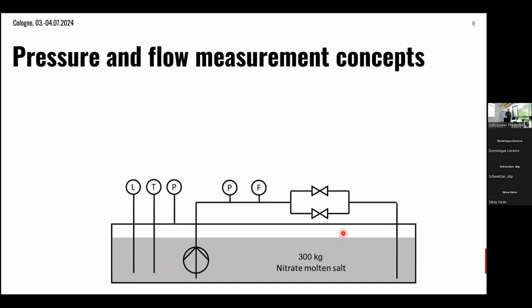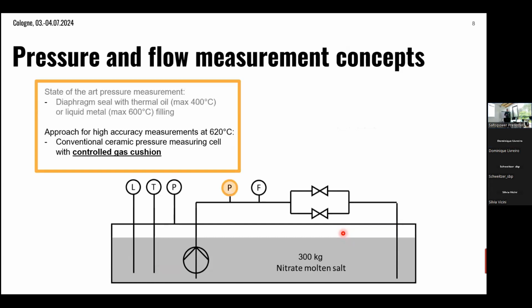So let me talk about the pressure and flow measurement concepts. For the pressure measurement, state-of-the-art pressure measurements use either diaphragm seals with a thermal oil that goes up to 400 degrees, and we also saw these Gefran sensors in the last presentation. They go up to at least 600 degrees, and they have a liquid metal filling. What filling? Liquid metal. Yeah, it's sodium, potassium.